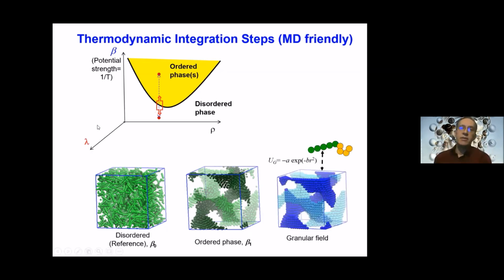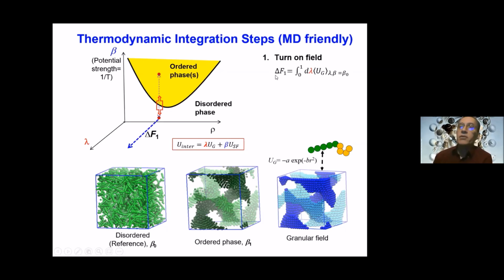So there'll be another axis, let's call it lambda. And the idea is as follows: given that you create this interesting geometry, you will use this to cast a mold of an external field that is going to bias the system into that structure. You can do that by creating a granular field where you will use these Gaussian beads that are going to selectively attract the rods, because we know that the rods go into those regions. But you are going to increase this potential in a gradual way. So we modify the Hamiltonian by adding this external field, this UG, that corresponds to these interactions. And when you turn it on, you do it very gradually, so that it goes from a structure that looks like this, disorder, to something that looks like this because of this bias.